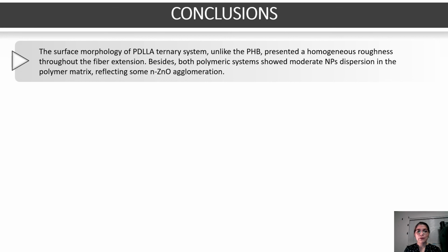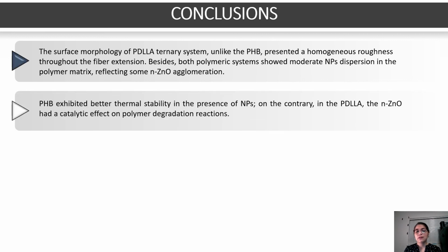Finally, as a conclusion, the surface morphology of PDLLA ternary systems, unlike the PHB, presented a homogeneous roughness throughout the fiber extensions. The PDLLA morphology was more attractive than the PHB for the application. PHB exhibited better thermal stability in the presence of nanoparticles. On the contrary, in the case of PDLLA, the zinc oxide possibly had catalytic effects on the polymeric degradation reaction.